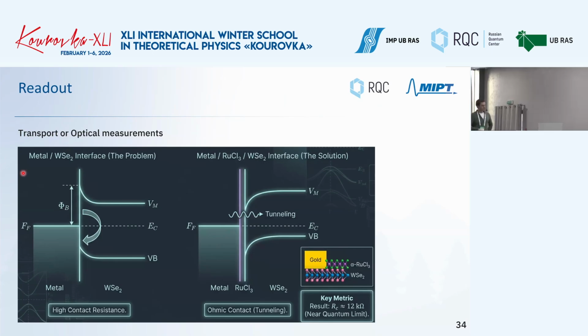People are demonstrating that, in order to do the detection in the transport measurement, the contact should be ohmic contact. So in order to measure just the resistance difference, the resistance should not be high. And it turns out in experimental realization that this is very crucial. Well, basically, it is very difficult for us.